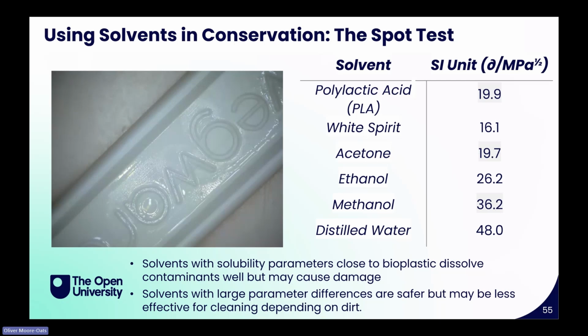And it's very important to say that we use conservation grade materials and chemicals, as you can see on your screen. And we use Hildebrand solubility parameters. To explain that, you see that they have specific numbers. And what that means is if polylactic acid has a solubility parameter of 19.9, and a chemical is closer to that number, it's more likely to dissolve or degrade it, right? So it can be more effective at cleaning any type of dirt. And the further away it is, the less damaging it is to the object itself, and it may or may not remove the dirt as well.